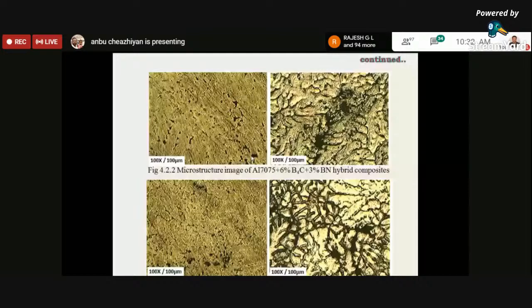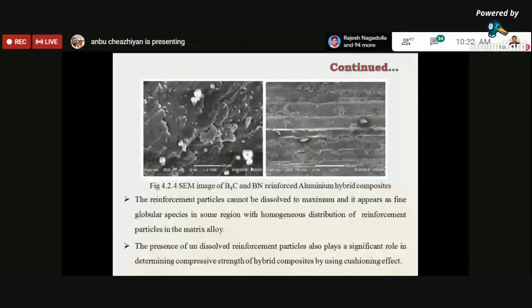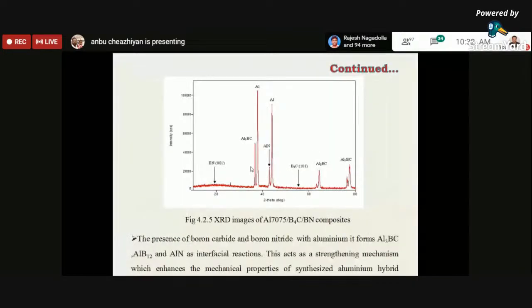Okay, so from the XRD analysis, it is clear that the strengthening mechanism occupies an important place in enhancing the mechanical behavior of aluminum hybrid composites. So here, the presence of boron carbide and boron nitride interacts with aluminum to form Al3BC, AlB2, and AlN interface reaction, and this is the strengthening mechanism which enhances the mechanical properties of the synthesized composites.